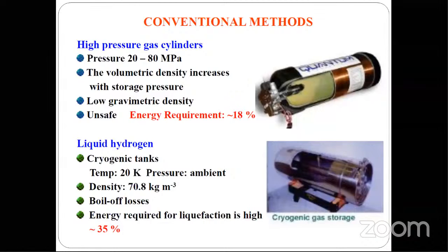The conventional method is first the high pressure gas cylinders. As I told, hydrogen is a very light gas, so it will take huge volume if you store it at atmospheric pressure. So to reduce the volume, we pressurize the hydrogen up to 800 bar. The volumetric density increases with storage pressure. If you increase the pressure, obviously the volumetric density increases. Hydrogen has very good gravimetric density, but the low volumetric density you can enhance by increasing the storage pressure.